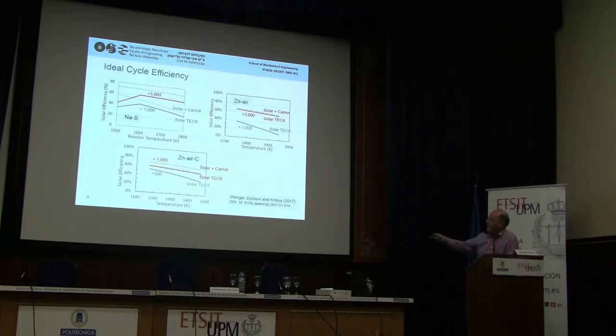If we add carbon to this mixture of zinc oxide, then carbon is a reducing agent that makes the reaction, the decomposition of the zinc oxide, a lot easier. And we can get similar levels of efficiency, something like 60%, at a temperature of 1,200 K, that is below 1,000 C. And this is a much more manageable temperature.